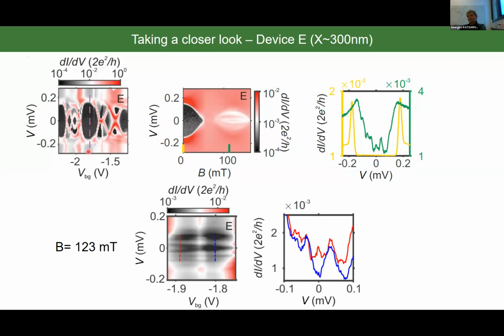And if now we fix our magnetic field at 123 millitesla, which is at the center of the first lobe, and we measure conductance versus bias and backgate voltage, you can see that the zero bias peak extends over a certain range, then it disappears. And you can see also all these additional subgap states, which we believe must be due to the fact that we have more than one pair of Andreev bound states.